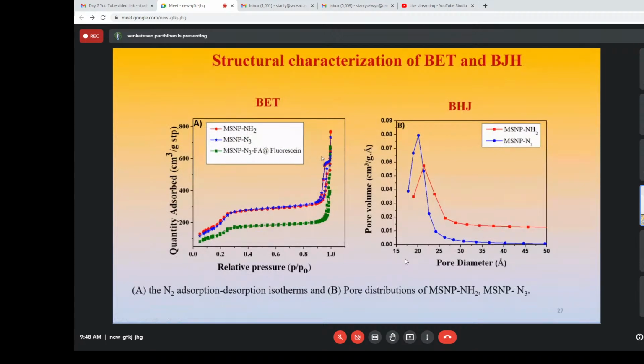After surface modification, further we need to make sure with the BET experiment, like the surface area and the pore volume. So we can see here initially only the mesoporous silica nanoparticle with NH2 functionalization. After further modification, we can see the surface area is decreasing because of the functionalization, or maybe dye is loading. Further the pore volume is also decreasing. So we can see initially only the NH2, further we attach the N3 side group. So that's why the pore volume is also slightly changing, or maybe decreasing.